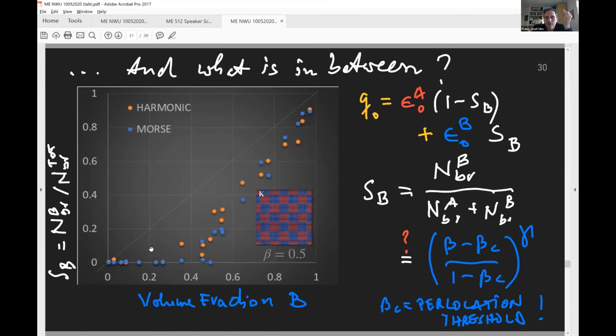But here we have phase B. So the blue phase is in smaller squares. So you must imagine that that would be something of the form that has small little squares here, right, of blue as I increase the volume fraction. And there are two phenomena which are of interest here. By the way, independent whether it's harmonic or Morse potential, so linear or nonlinear fracture mechanics, you see that there is here a percolation threshold, which you would expect, right?